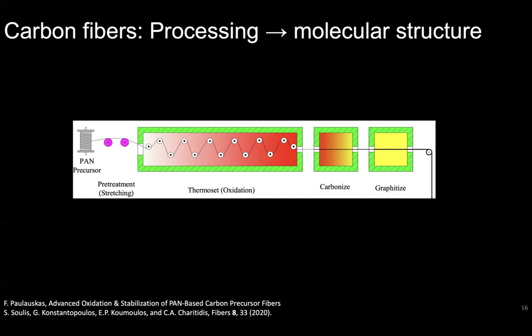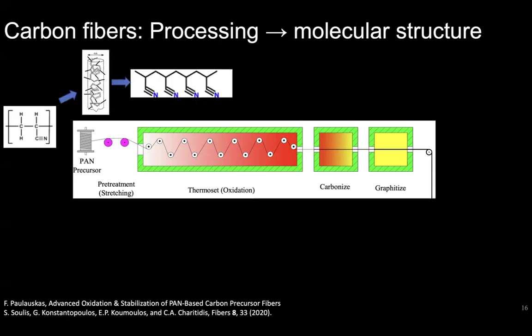So carbon fibers that are used, as you know, to lightweight anything from aircraft to cars and bikes, competitive bikes. You start with a polymer called PAN, polyacrylonitrile, and the first thing you do is you spin it. And when you spin PAN, you kind of align the chains of the polymer. So the chains become stretched, and so you have a multi-phase polymer with amorphous regions where the chains are all twisted and more ordered regions.